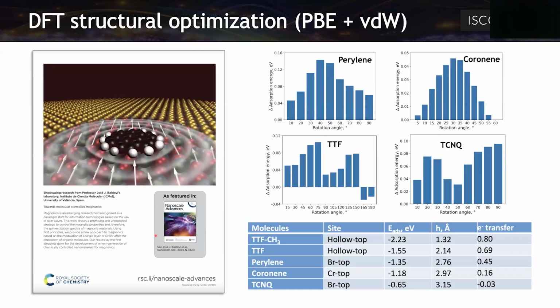And this work was published very recently in Nanoscale Advances, and you can check there all the calculations that we performed. It was more than 1 year of calculations, because it takes a lot of time on this kind of systems. And we observe also that, for example, in the case of perylene and coronene and TCNQ, they are in this position that we found. They are in this perfectly aligned orientation on top of one atom and taking directly one of the axes in the material. But in the case of the TTF, the most stable calculation is 165 degrees. So the molecule is tilted, and it's also tilted towards a bromide that we will see in the next slide.